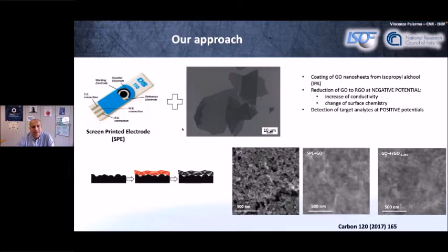And here you see an image of these screen printed electrodes, the original one, so you see how they are, all these conductive particles. When you coat them, you have a much flatter surface, and this is the central image, these electrodes coated by graphene oxide, so it's partially insulating. But then electrochemically or thermally, even chemically, you can reduce it. And in this case, because you are on an electrode, it's very easy just to apply a negative potential and you reduce this graphene oxide, going back to reduced graphene oxide. And of course, you can tune it very well, because in this case, applying minus 1.25 volts, you get to a certain reduction grade. You can apply higher or lower voltages and stop where you want.